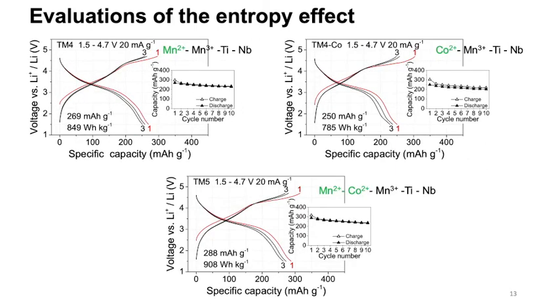In the second group of comparison, we compare two different TM4 compounds. The first one contains manganese 2 plus, manganese 3 plus, titanium, and niobium. And the second one contains cobalt 2 plus, manganese 3 plus, titanium, and niobium. We compare those two compounds with another TM5 compound, which contains all 5 elements: manganese 2 plus, cobalt 2 plus, manganese 3 plus, titanium, and niobium. And we can see this TM5 compound shows a higher capacity compared to both of the TM4 compounds. This proves cobalt itself cannot explain the improved capacity from TM4 to TM5.